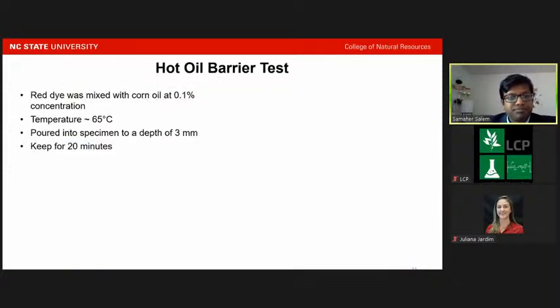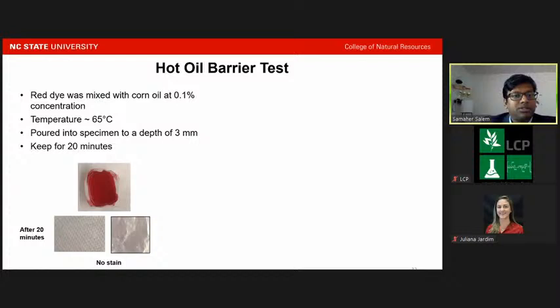So then we also did the hot oil barrier test. We used red dye mixed with corn oil at 0.1% concentration. We kept the temperature at 65 degrees Celsius and poured the oil onto the specimen to a depth of 3 millimeters and kept it for 20 minutes. And you could see that after 20 minutes, there is no stain, which shows that the cellulose film passed the hot oil barrier test.